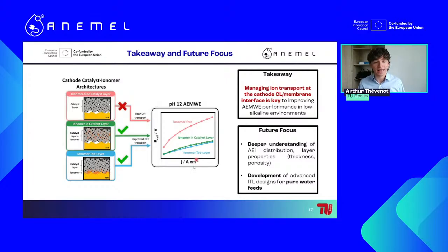But then afterwards, we wanted to check the mechanistic insights to understand the role of this ionomer top layer in the system. And we saw that even in abundant OH- medium, the ionomer top layer was still superior to the ionomer-free catalyst layer. And therefore, this led us to the hypothesis that the ionomer top layer is optimizing the interface, this two-dimensional frontier between the cathode catalyst layer and the membrane.